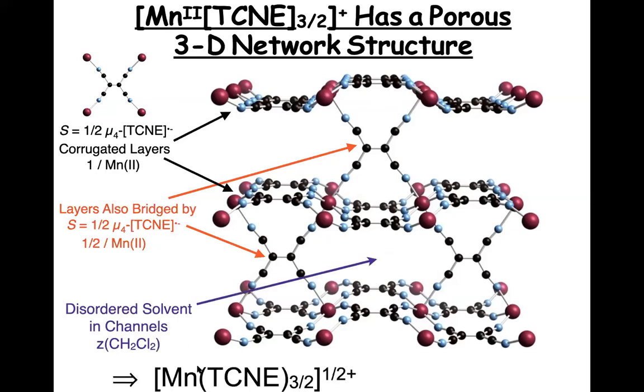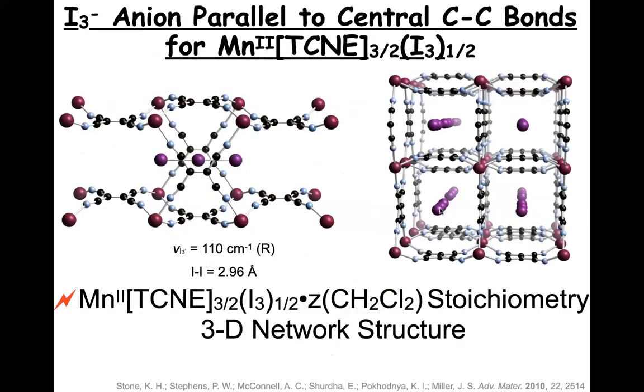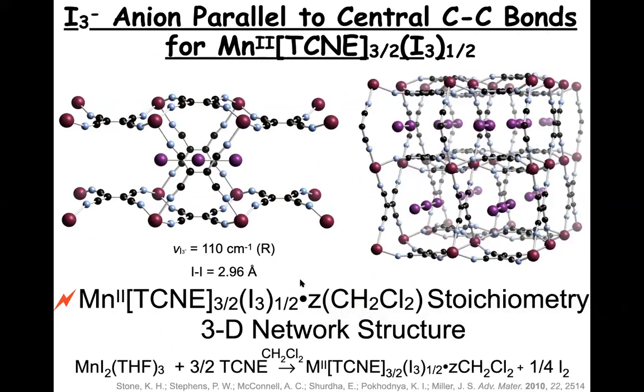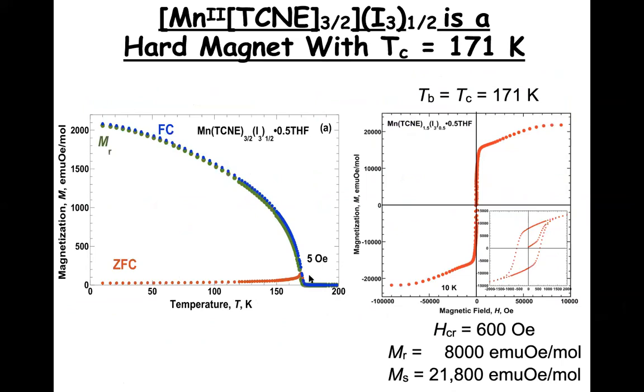And in this particular case, we have 1.5 TCNEs per manganese, a net plus 1/2 charge, and the counter ion, unknown at this time, turns out to be triiodide, half of which is floating in the structure. This material actually is now not an antiferromagnet, but a ferrimagnet that orders at 171 Kelvin and has hysteresis loops of the type you should expect to see for a bulk magnetic material.